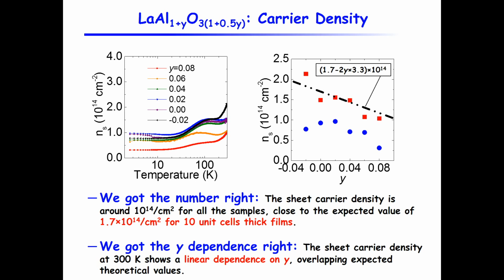And this line here is (1.7 minus 2y) times 3.3 times 10 to the 14th. That is what people should expect for films of 10 unit cells with different stoichiometry. It's not 3.3 because it's 10 unit cells. You only get 3.3 when you go to a sufficient thickness.